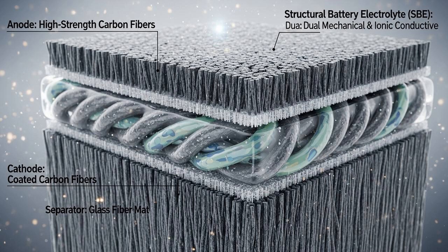This is the special sauce. It's a multifunctional matrix that has to do two opposite things at once. It needs to be mechanically strong to transfer loads between the carbon fibers, like a solid resin. But it also needs to be ionically conductive to let lithium ions move between the electrodes, which is a job usually done by a liquid.